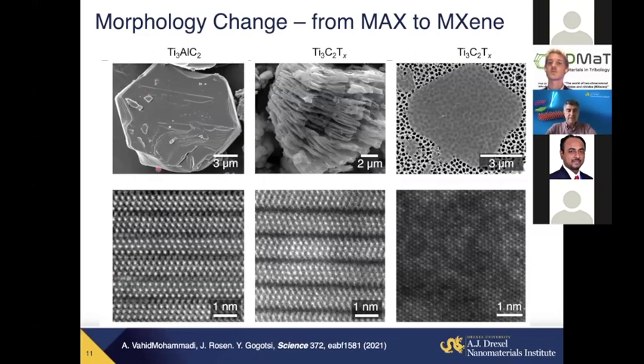Hexagonal particle of a typical MAX phase. These three bright layers of atoms are titanium atoms in this case. The layer connecting them in this particular example is aluminum, titanium 3 aluminum C2. We etch it in an acid. You can see the particle changes, becoming very much like a thermally expanded graphite. And aluminum is gone, but you may notice surface terminations that appear on the surfaces here, less bright atoms terminating the surface. And when we separate them into a flake, this is a single layer flake of titanium 3C2.